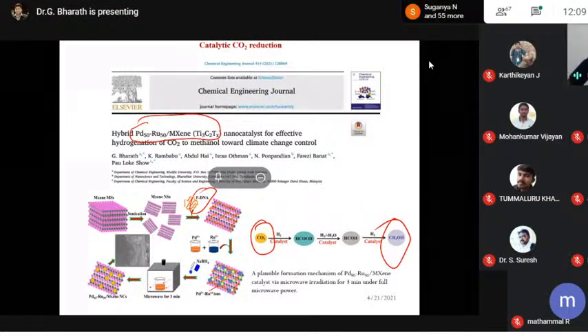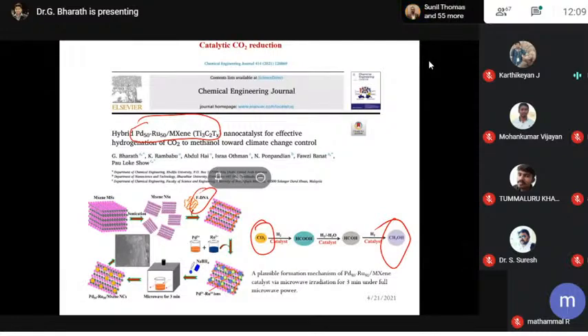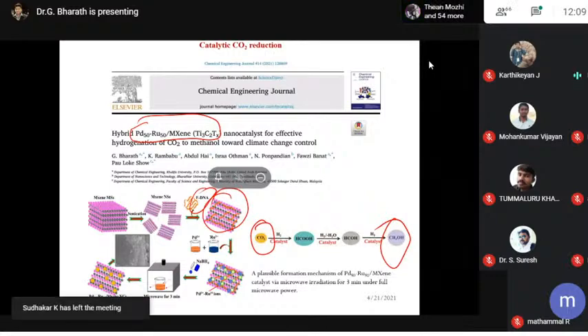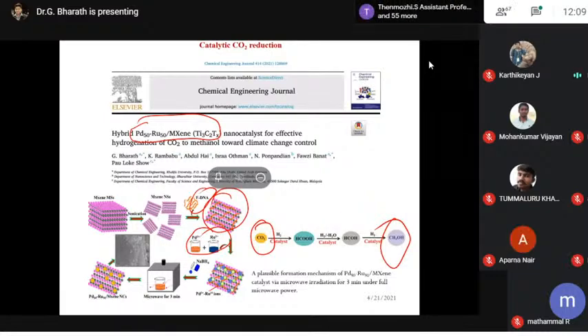Anchoring site for metal nanoparticles. Here our metal nanoparticle is palladium and ruthenium. Once we functionalize this MXene, and then add palladium and ruthenium chloride as reactants, we successfully converted these palladium and ruthenium ions to palladium-ruthenium using sodium borohydride. Sodium borohydride is a very strong reducing agent.